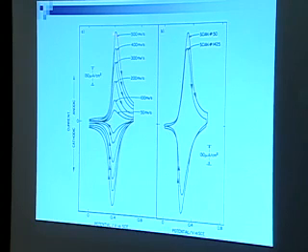And we have a linear scan rate dependence. You'll notice here's 200 millivolts, for example. If I go up twice the distance, there's 400 millivolts. Cut 200 millivolts in half, go half down, there's 100 millivolts. So a very linear scan rate dependence over this whole range from 50 millivolts per second to 500 millivolts per second. Only one order of magnitude, but that's good enough.